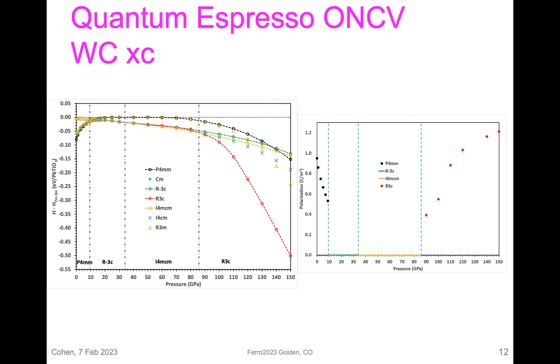The interesting thing is that at 85 GPa we're finding it to be ferroelectric again — so we can't really say that Kornev and Bellaiche were wrong. They were just right eventually. If you look at the polarization, you can see it drops and goes to zero, then comes up again and looks quite ferroelectric. So that doesn't seem consistent with the experiments, and that's why I've sat on this for a while.